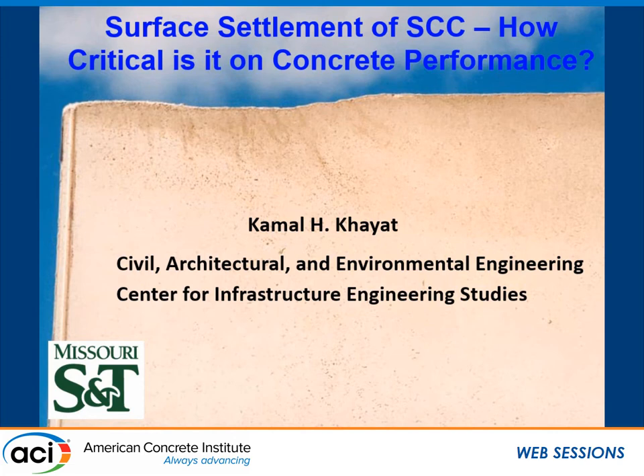SCC, as you know, is a concrete that has to have very specific rheological properties to ensure that what you see over here does not happen after you strip the formwork. This is a typical surface settlement issue that you can get when the concrete is not stable. And I think the previous presenter told us about settlement and factors contributing to this.